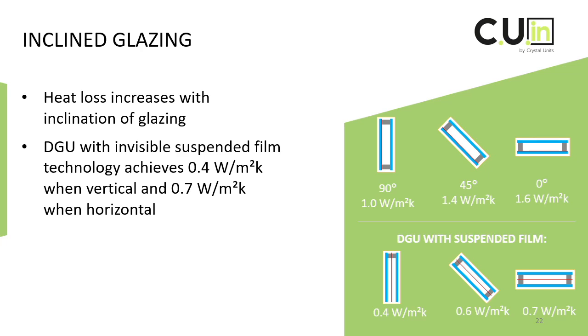The suspended film technology is the ideal solution to meet the U-value requirements. As the diagram shows here, double glazing with suspended film technology achieves 0.4 watts per meter squared Kelvin when vertical, and only rises to 0.7 watts per meter squared Kelvin when horizontal.